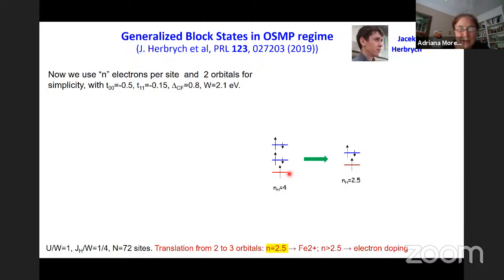In the orbital selective Mott phase, we have the Mott orbital that has a localized spin with population 1, and the other 2 orbitals had population 1.5, as I showed in the previous figure. So we went from 3 to 2 orbitals in this particular phase by writing a 2-orbital model with 2 orbitals and a doping of 2.5, because we think this distribution of electrons will capture the behavior.